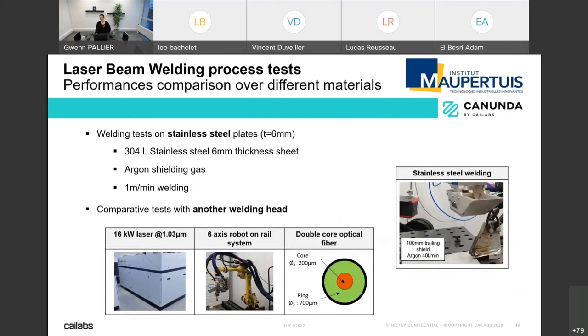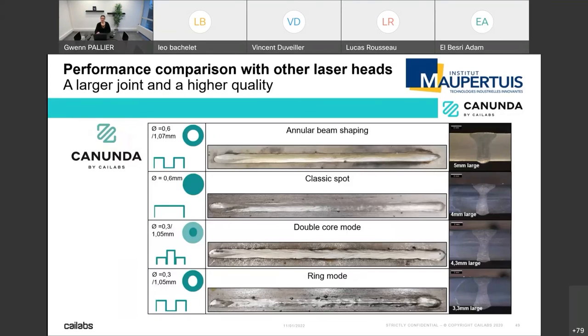I will try at least to mention some, of course, actual process results. So we were doing some stainless steel welding in this configuration. What we got with our system is the weld on the top. So we were having energy only on this very ring. It's the Canunda product. And as you can see, we have a very nice weld. And this is a macrograph of the weld with a very large weld, which means that it's very stable, very robust, and it's also very smooth.